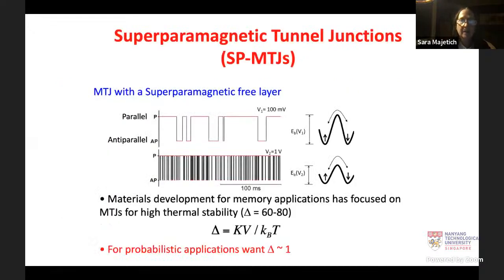Again, a superparamagnetic tunnel junction is a regular tunnel junction with a superparamagnetic free layer. If we're looking at current as a function of time, then the parallel state would have high current, the anti-parallel would have low current. If you have a big barrier, you would have a fairly long dwell time on average before the next switching event. If you have a low barrier, then you'd have a short dwell time before switching events. In the case of current, the parallel is high and anti-parallel is low. If we're looking at resistance, it would be the opposite.